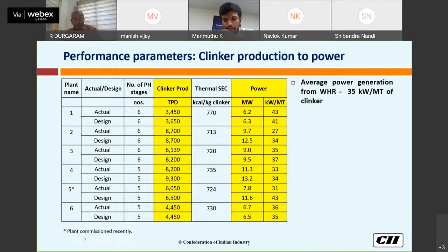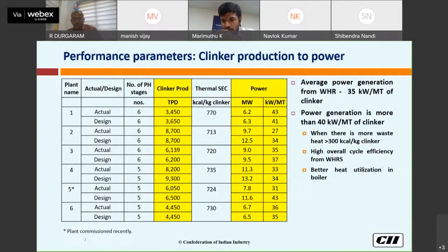So based on the table, the average power generation from WHR in India is around 35 kilowatt per metric ton of clinker, and one of the units generates more than 40 kilowatt per metric ton, where there is more waste heat, greater than 300 kilocalorie per kg. As I said, around 42% of heat we are wasting. In this there are some avoidable losses. If it is greater than 300, it can generate 40 kilowatt. And if the overall efficiency of the WHR is good, this also adds value to generation, and better heat utilization in the boiler is also a factor.